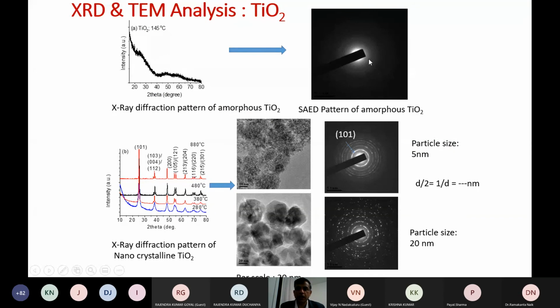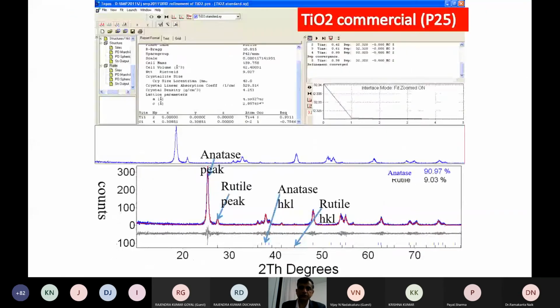So this is the TEM data, and if it is a really small nanocrystalline material, we can see this type of circular rings, or with improved crystallinity, we can see dot patterns. Usually in TEM, the circular ring diameter, divided by 2, gives 1 over D, which gives the information about the D value. The nearest D value belongs to a particular plane, and that way you can match. That's why it is very important to know the XRD, so that you can interpret the TEM data.